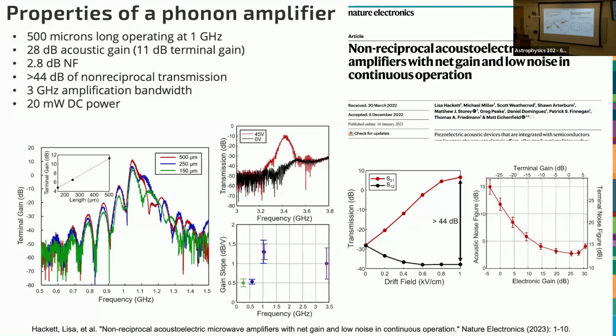Now I mentioned that if you turn the acoustic wave around in the opposite direction, it will be heavily attenuated. How much? Well, we get about 44 dB of non-reciprocal transmission, meaning it's a little bit more than 20,000 times higher transmission in the forward direction than attenuation in the backward direction. So very, very non-reciprocal. The bandwidth of the amplifier: the center frequency is designed to be about 1 gigahertz, but we can put multiple of these IDTs down on the same wafer and characterize the bandwidth of this single layer of material. And we have about a 3 gigahertz bandwidth. So it's very, very broadband.